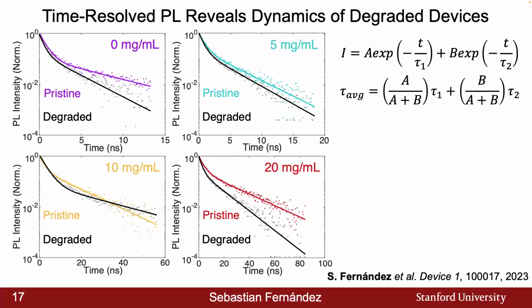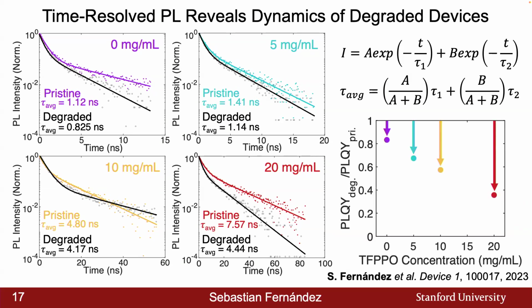Additionally, we can also define an average of these two lifetimes, so both with their contribution of A over A plus B and the tau 1 and tau 2 accordingly. And by annotating these tau averages together, we can see that in general, with higher TFPPO concentration, we see a greater reduction in the tau average. And this is largely due to both the contribution to tau 2, which is B over A plus B, as well as a reduction in the tau 2 lifetime, which is related to the emissive and radiative recombination nature of the perovskite thin film.